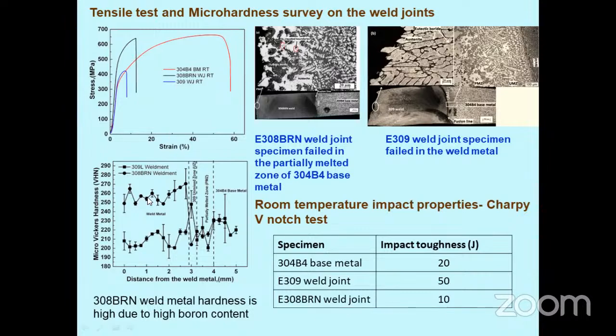When we see the micro hardness results across the weld joint, we see that the 309 boron free electrode has a more or less uniform hardness distribution across the weld joint. In case of the boron added electrode, we have a higher weld metal hardness as compared to the base metal because of borides present in that.